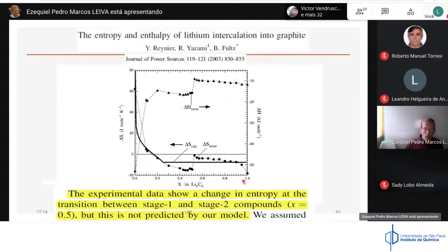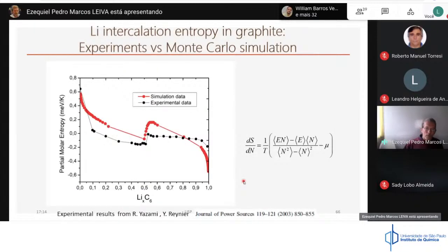Well, the point is that we have simulated the partial molar entropy with the previous model, and we get good agreement with this experiment. These red are simulated data, the black ones are experimental data, and they show that the model is able to reproduce the behavior of this system. What is the origin of this step in the partial molar entropy?